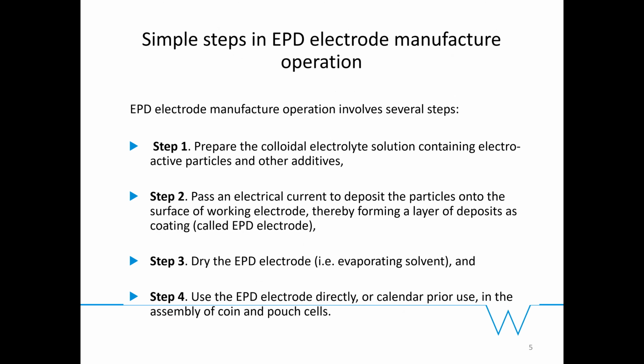So as I mentioned before, the EPD process requires colloidal electrolytes, which are electroactive as well, and sometimes additives are also added, such as binding agents to ensure that the electroactive species stick onto the surface of the foil, for instance aluminum foil, and also charging agents to enable easy transport of these particles onto the working electrode.